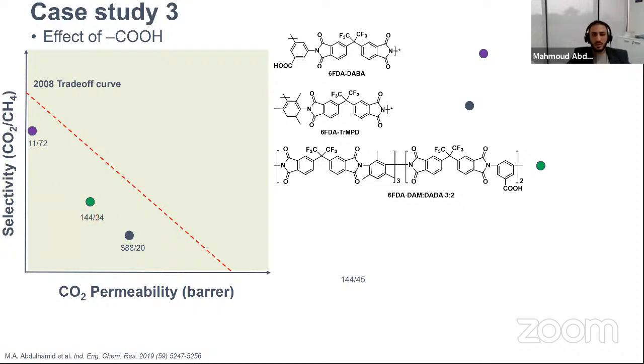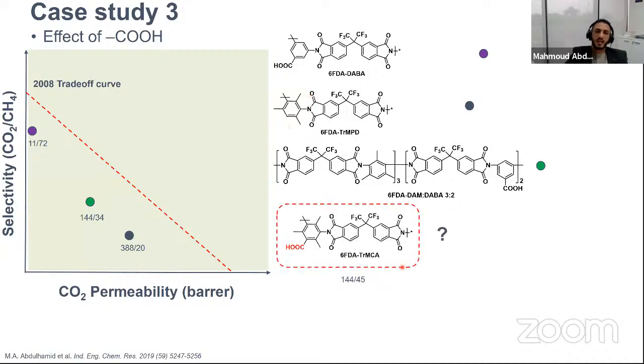same time. So we thought, why do we have to go for a copolymer? Why don't we just make a new polymer that combines these two parameters, having COOH and having trimethyl groups here? So we designed this type of polymer. This polymer has a polar group, so we can study it and see the effects of this polar group. And it has the trimethyl group, so we can compare it to this one as well.